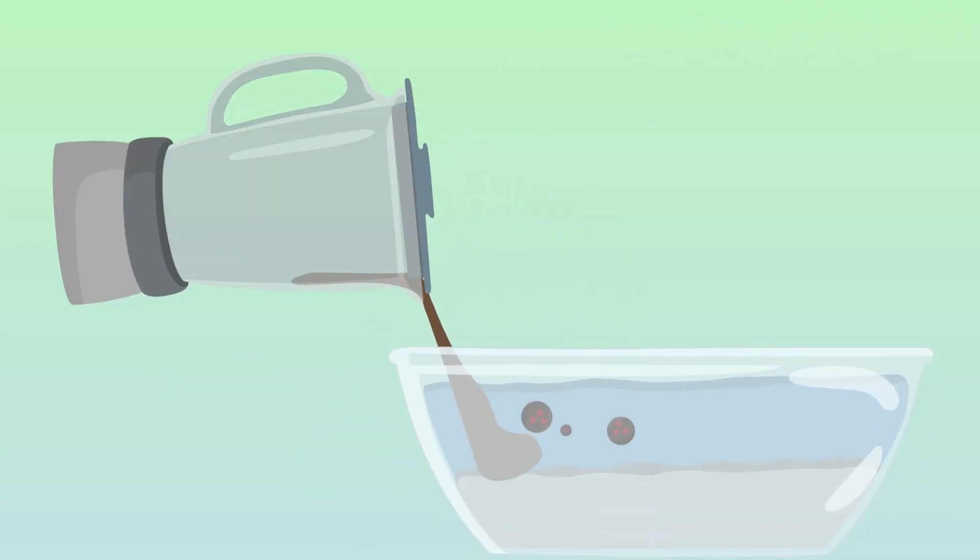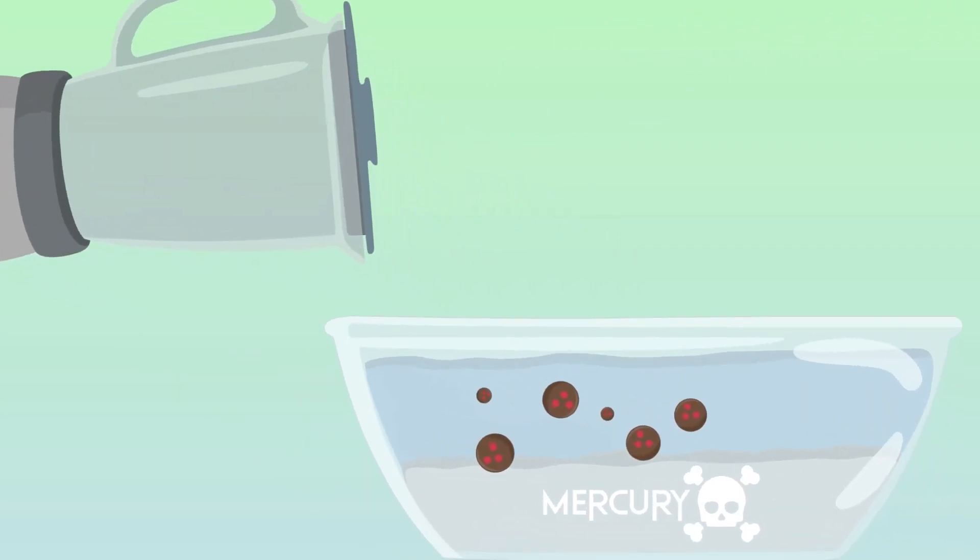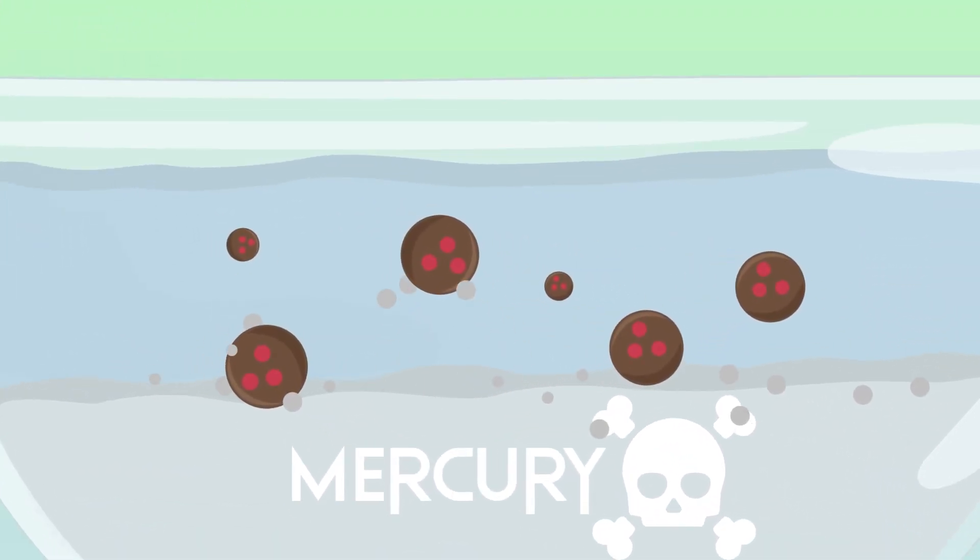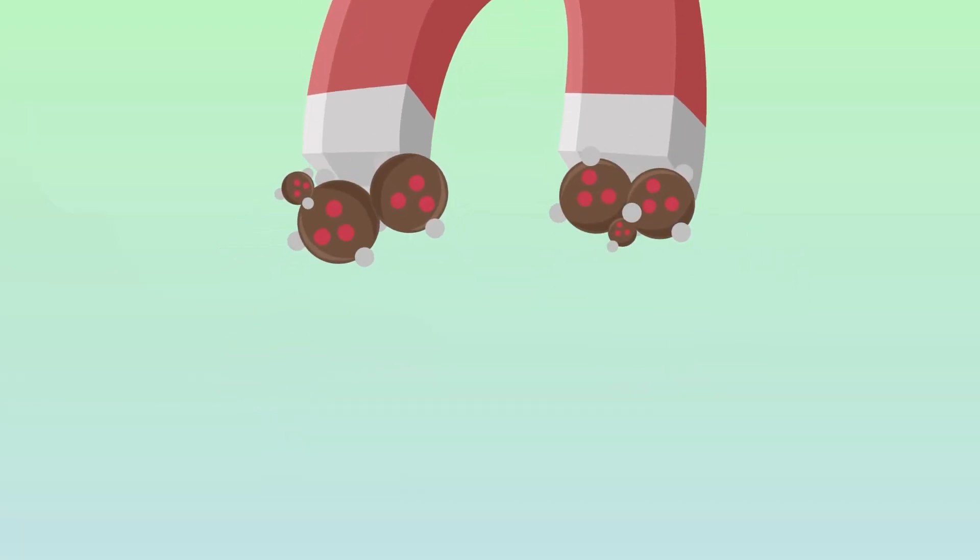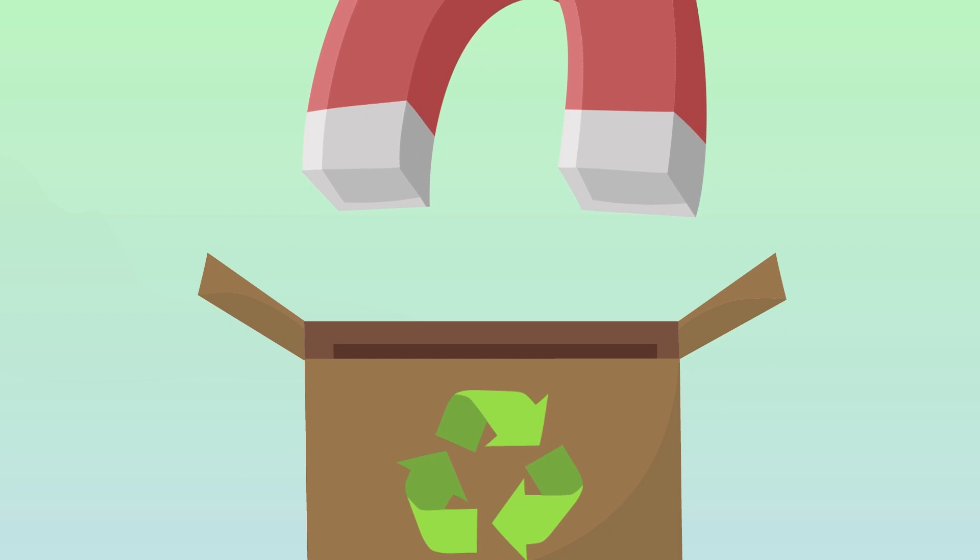When blended into a powder, it can be used to purify mercury-contaminated water like a sponge. This is because sulfur in the polymer binds heavy metals, while the magnetic nanoparticles allow it to be safely picked up, cleaned up, and recycled.